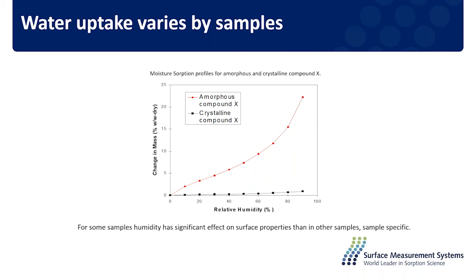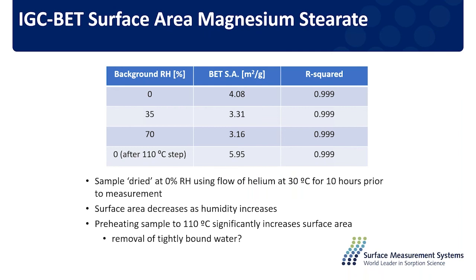Because there's humidity everywhere during production, during the application of solids, during processing also. So that can have an effect on surface area. Quick example for magnesium stearate. We measured surface area at 0, 35, and 70% relative humidity. In the case of magnesium stearate, you can see there's already a significant decrease in the first step, but after that, increases in humidity didn't change the surface area much.